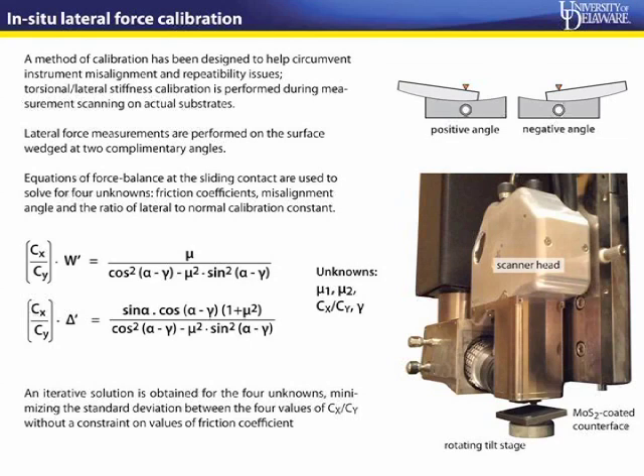Now you'll notice that we have one unknown in CxCy, one unknown in mu, and one unknown in gamma. So what we do in this method is scan on two angles. This illustration shows a positive and a negative angle. That gives you four equations instead of two, because now you have alpha 1 and alpha 2. Cx, Cy, and gamma are the unknowns, and then mu1, mu2 on the two different angles give you the two other unknowns. So you end up with four equations and four unknowns.